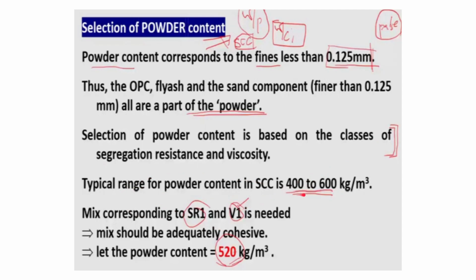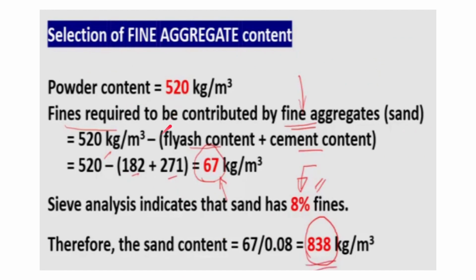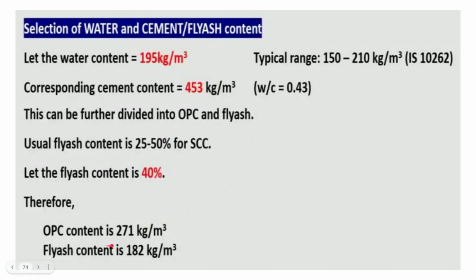So powder content should be in the range of 400 to 600 kg per meter cube, which is adequate for self-compacting concrete, and a mix corresponding to SR1 and V1 is needed. So the mix should be adequately cohesive, because SR1 V1 requires this. We have assumed here the powder content is 520 kg per meter cube, because it should be between 400 and 600. So let us assume 520. So 520 is the required powder content, and we have the cement content of 453, where OPC was 271 and fly ash was 182.